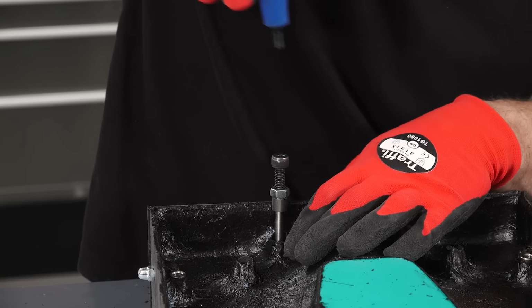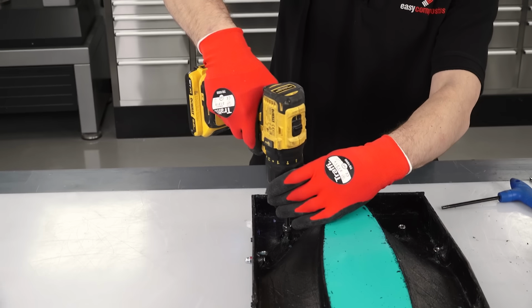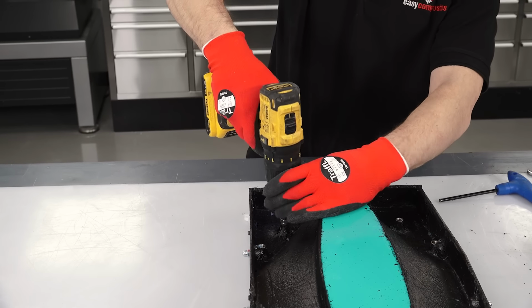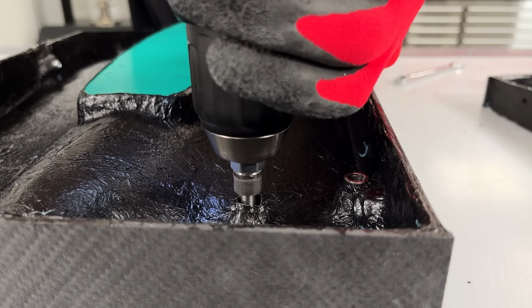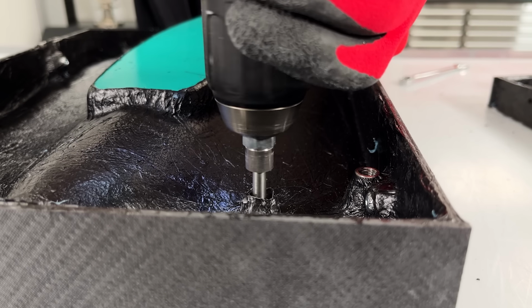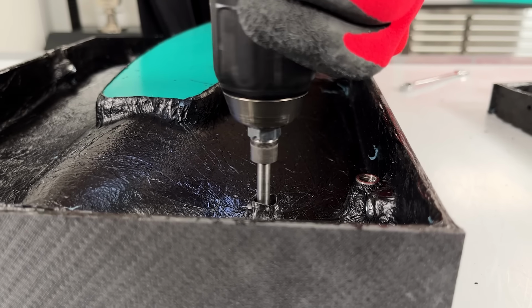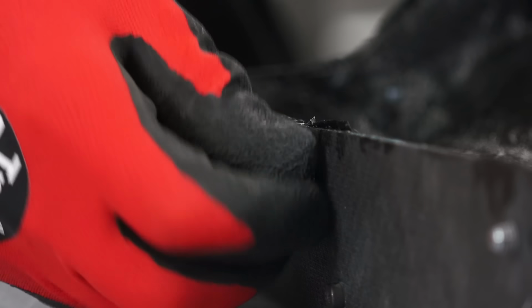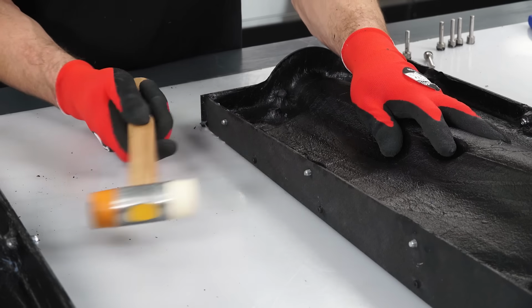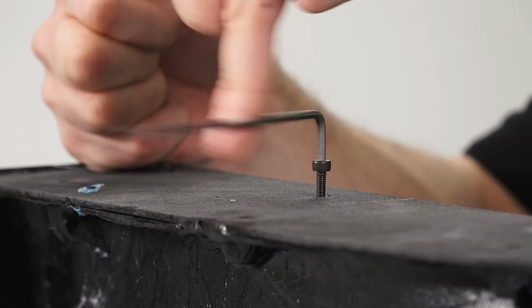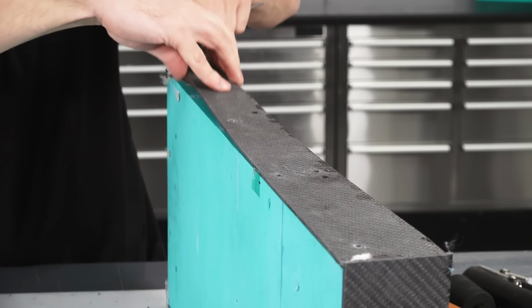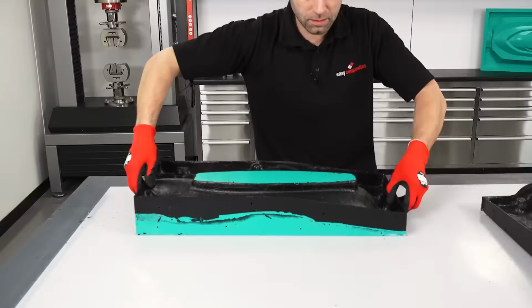extract the pin. It's also possible to use a cordless drill to twist and pull the pin, but do be careful to only use a very slow speed when doing this, otherwise the pin can get very hot and potentially damage the surrounding prepreg and tooling board. Once all of the pins have been removed, there's really nothing holding these moulds onto the patterns, and they remove very easily.